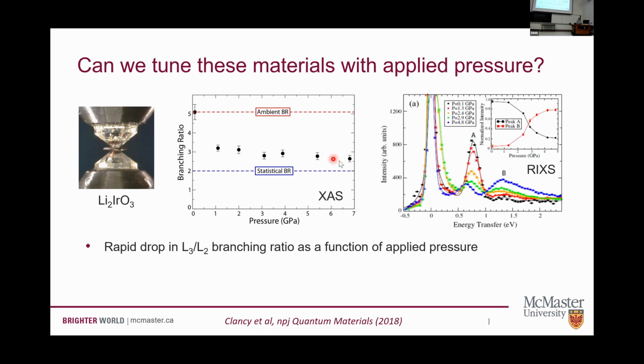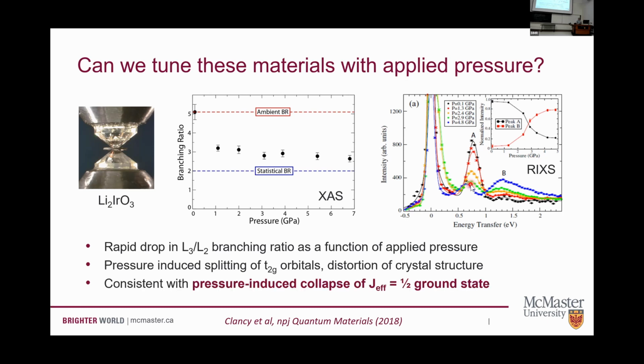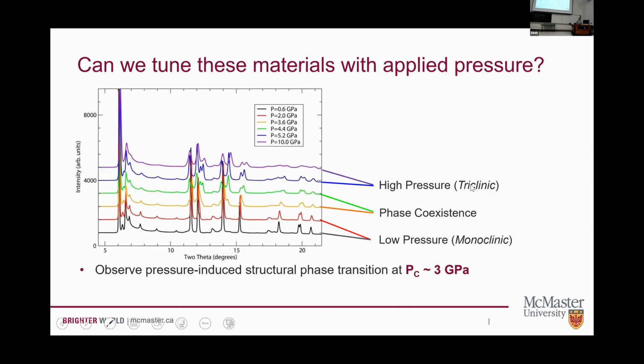What does the RIXS spectra look like? We get a lot of splitting of these orbital features that we were looking at before. So the combination of these two results suggests that when we're applying pressure, we're basically destroying this J effective 1/2 state. So we make our structural distortions larger, and that gets rid of this nice balance of crystal field and spin orbit coupling. So we enter a new, more complicated regime.